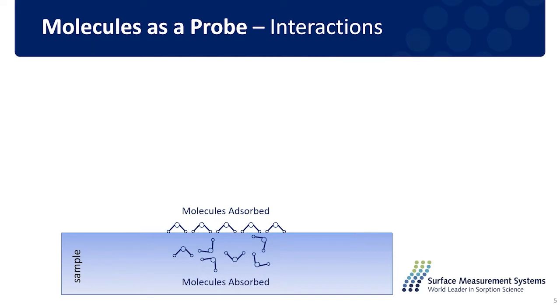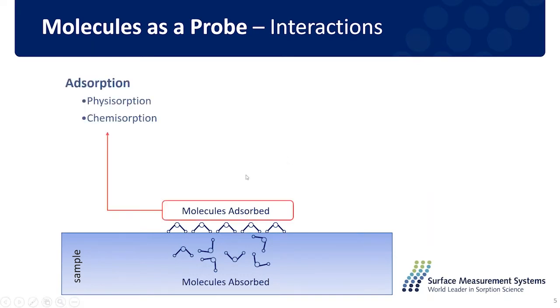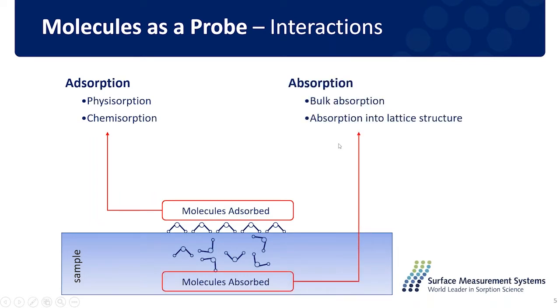From the uptake of mass, the change at different concentrations, we can detect lots of different interactions, by chemisorption and physisorption on the surface, where we can get all the surface-related properties like surface area and surface energy. Or we can get lots of properties related to the bulk, like the vapor-induced phase change or the formation of hydrate or solvate. So with the DVS technique, we can switch between different probe molecules and change the temperature and humidity we are interested in, and then we can determine all the properties we actually use in the practical application or the processing of the material.